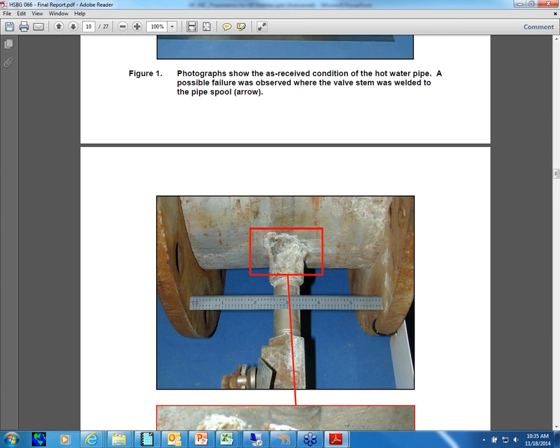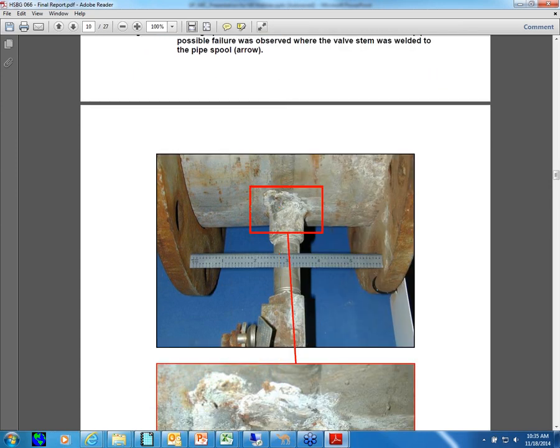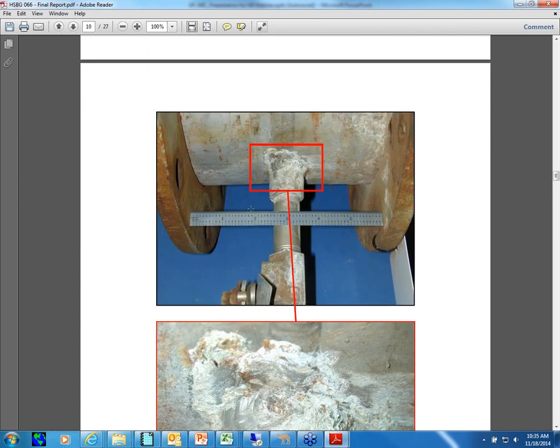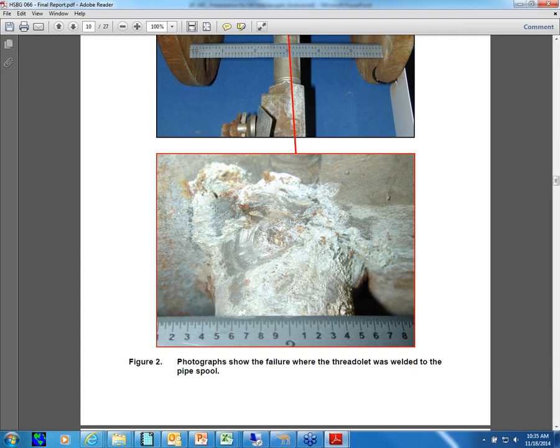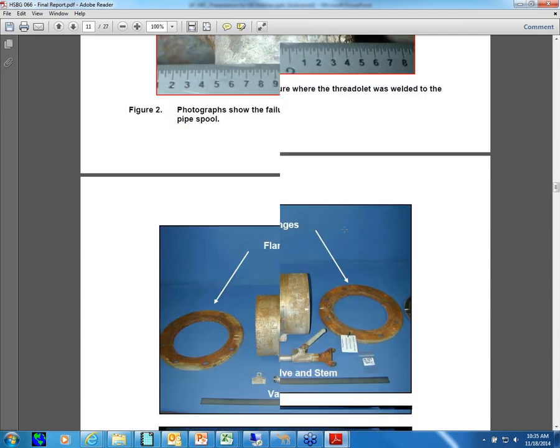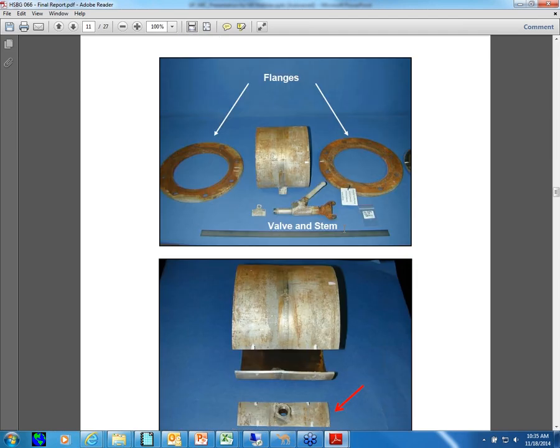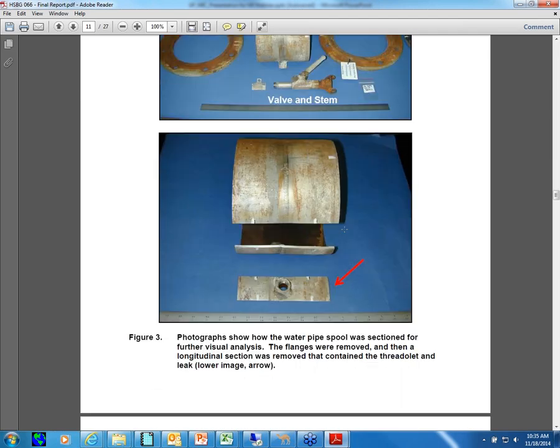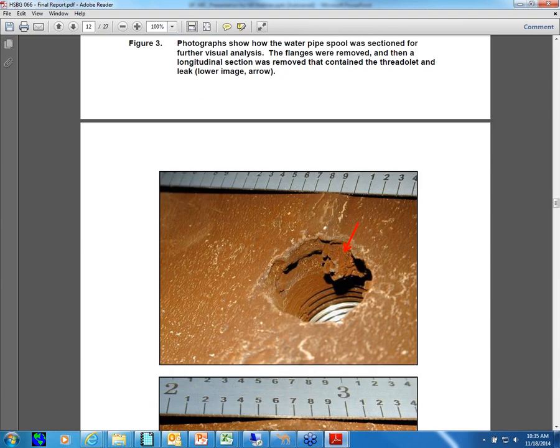And we had a chance to remove this one without an outage, so we could plan and just do it anytime we wanted to. So that's why we pulled this sample out of the line. It seems small and irrelevant, but it's actually one of the keys to us finding the solution to our problem. This is all we could see from the outside, but we assumed we might have MIC there. So we sent it for metallurgical analysis, and they pulled it apart, cut it up. And this is actually what they found, one little tubercle growing on the inside.